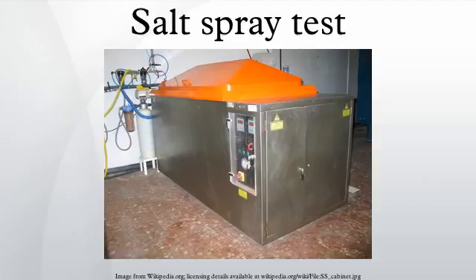ASTM G85 Annex A1: acetic acid salt spray test. This test can be used to determine the relative resistance to corrosion of decorative chromium plating on steel and zinc-based die casting when exposed to an acetic acid salt spray climate at an elevated temperature. This test is also referred to as an AASS test.